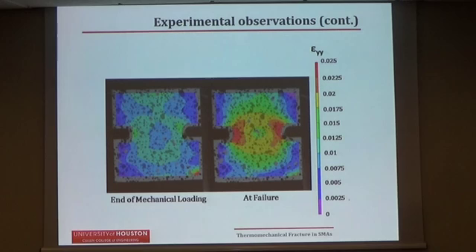But although it should play a role, we believe that it is not the defining factor, and the reason is that in a similar situation in the ductile to brittle transition in BCC materials, the change in the yield strength is around 200–300%, whereas here the change in the yield strength between the martensite and austenite is around 20–30%. What we believe is the defining factor is the stress redistribution coming from extended phase transformation. So imagine all those transformation strains of the order of 3, 4, 5, 6% distributed all over the place in the material. These transformation strains, imagine them as eigenstrains, they should have an impact on the mechanical fields close to the crack.